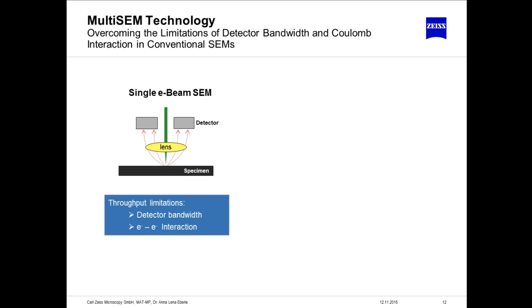Each detector usually has a given temporal bandwidth because it needs a certain time for recovery. Otherwise, the signal cannot be resolved anymore. On the other hand, another limitation that comes into play here is the signal to noise. If we scan too fast, then the signal we produce is not high enough to generate an image. So one way to deal with that would be to increase the beam current, which gives you more signal. But as electrons are charged particles, if you increase the beam current too much, these charged particles begin to see each other. They begin to repel each other. And this in the end would mean that you lose the focus on your sample surface and therefore the resolution.